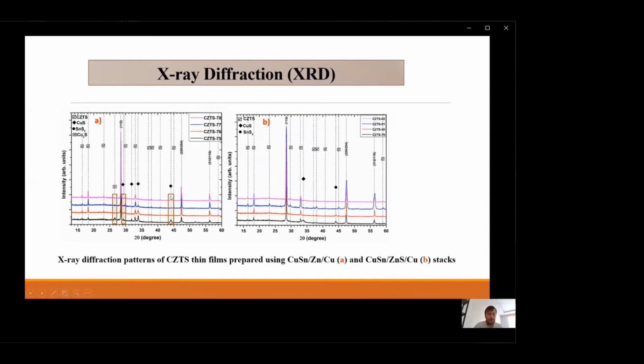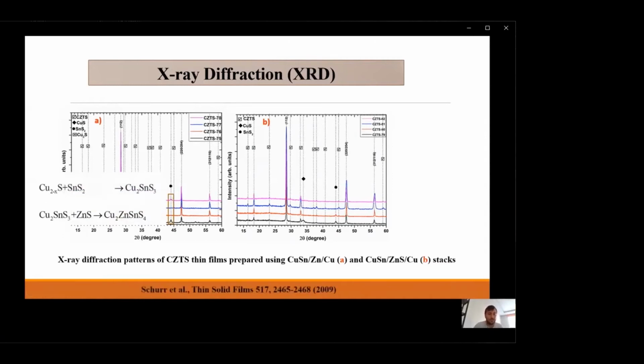This is an important result since, according to Schurr and his colleagues, as the temperature increases, these reactions are reversible. So if you increase temperature above a certain temperature, some decomposition reaction can occur. So in these samples, maybe some decomposition reactions occur since the tin sulfide phase forms here.